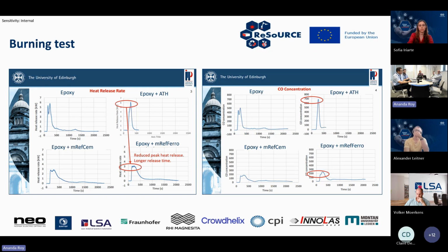So as you can observe, the epoxy system has a very high and sustained HRR, or the heat release rate, but the ATH also has the same sort of properties, which you can observe over there. But within the materials of the mRefCem and the MREF-Ferro composite, you can see a substantially reduced peak heat release is observed, also indicating that the suppression of this combustion reaction is taking place. But more as acting as a physical barrier for toxic gases such as carbon monoxide and carbon dioxide, you can see the same sort of behavior which you can observe within the epoxy and the ATH as well.